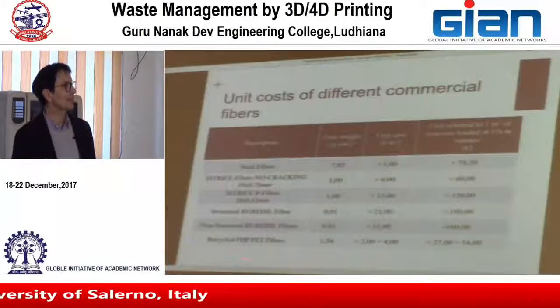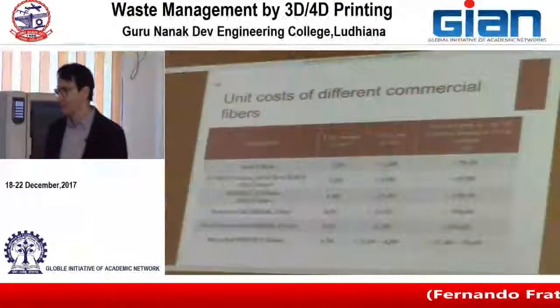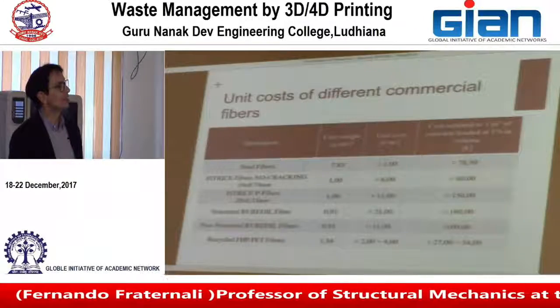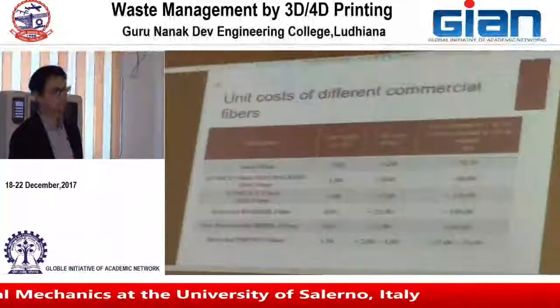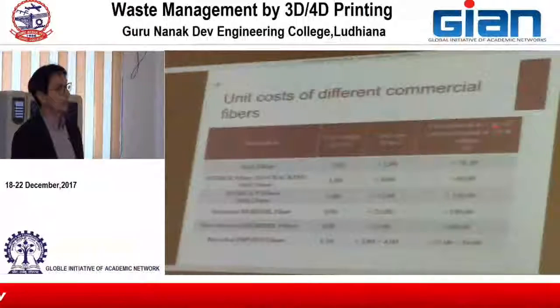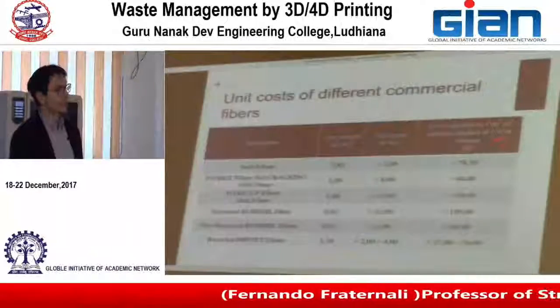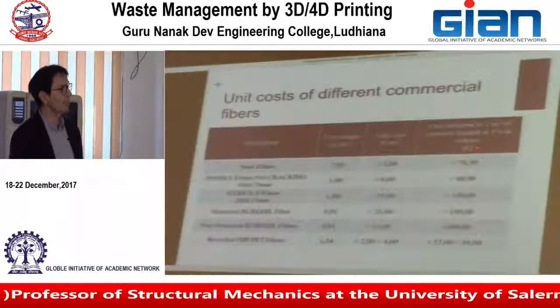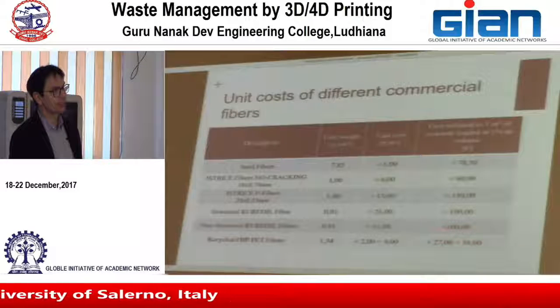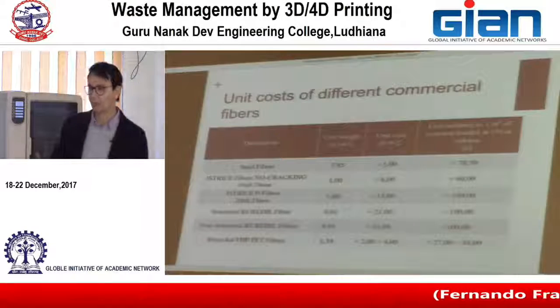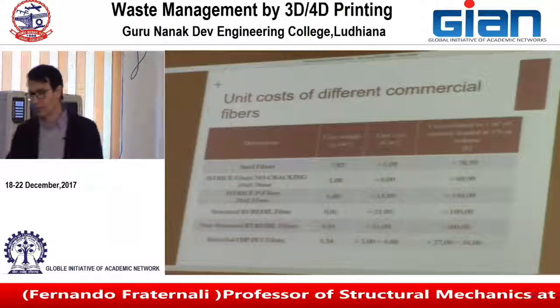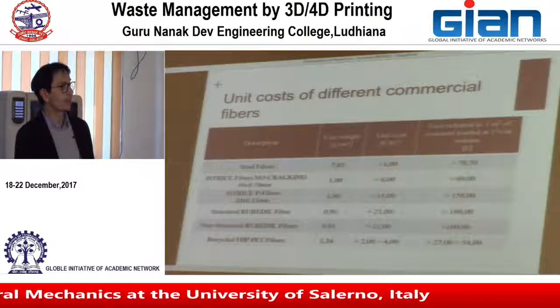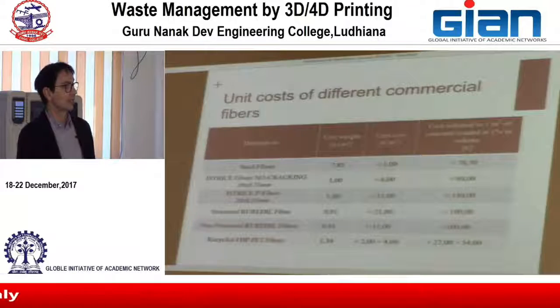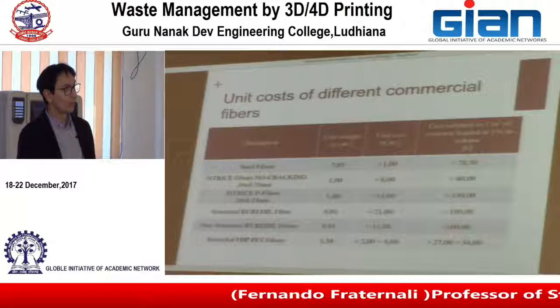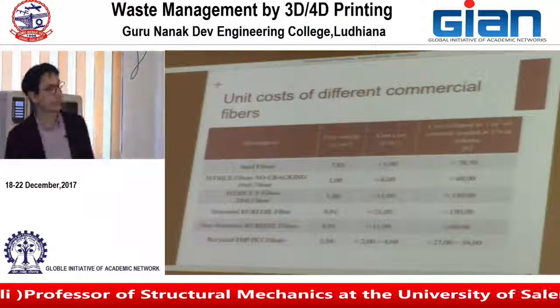We also run a cost analysis in this case. And what is surprising is that the plastic fibers are not cheap at all. Steel fibers have a given cost in euro for a cubic meter of material at 1% loading volume fraction. And our fibers, we estimated the cost through the company that was producing the fibers industrially, so they estimated the cost per cubic meter of those recycled fibers, and this cost was much less than the cost of commercial plastic fiber. It could be even 1/4 or 1/2 of the cost of commercial plastic fibers.